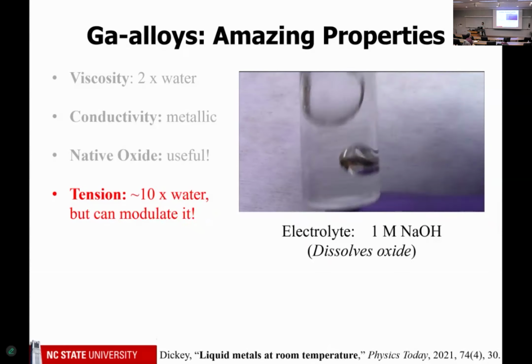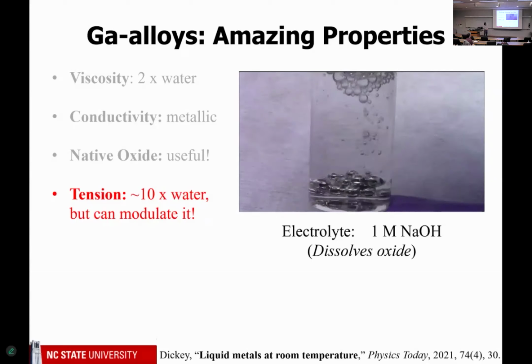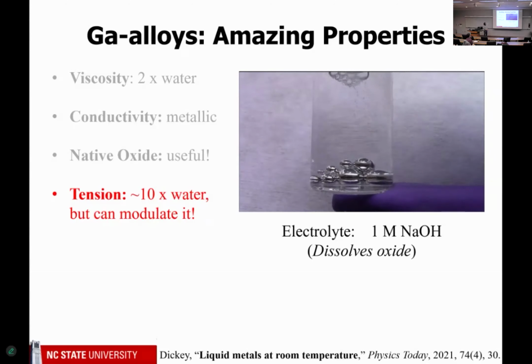Okay. So one last thing I want to show you about liquid metal is I mentioned it has a very large surface tension. In fact, 10 times the surface tension of water. So if you put it in base, sodium hydroxide, so there's no oxide, if you shake this, it breaks up into droplets, just like salad dressing. But as you can see in the video, it very quickly goes back together. So this, does anybody know the surface tension of water? This might be helpful.